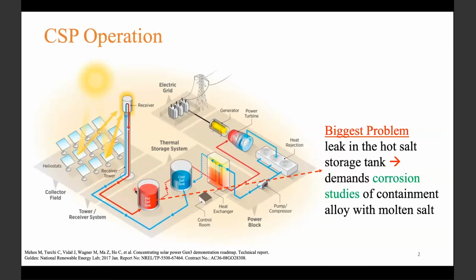So I invested my research at RPI to understand the corrosion of these containment alloys, that is Inconel, with molten salt mixtures. For the first time ever, I attempted to closely look at the high temperature corrosion of these alloys in real time inside a high resolution microscope, a transmission electron microscope, that also empowered me to analyze individual grains of the alloy. That means very small regions of this metal alloy.